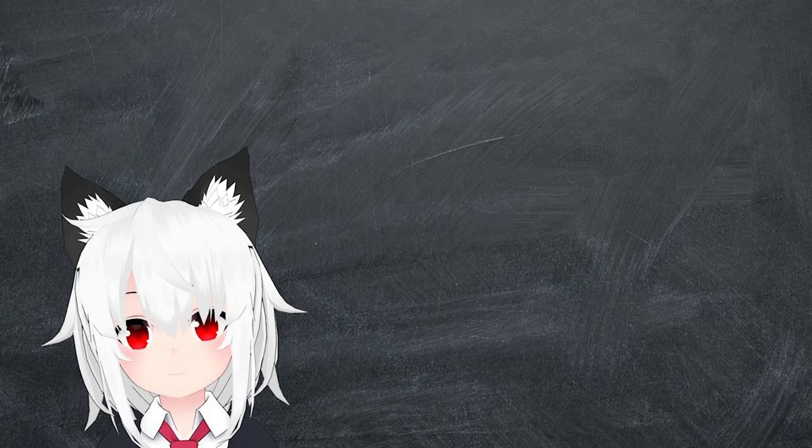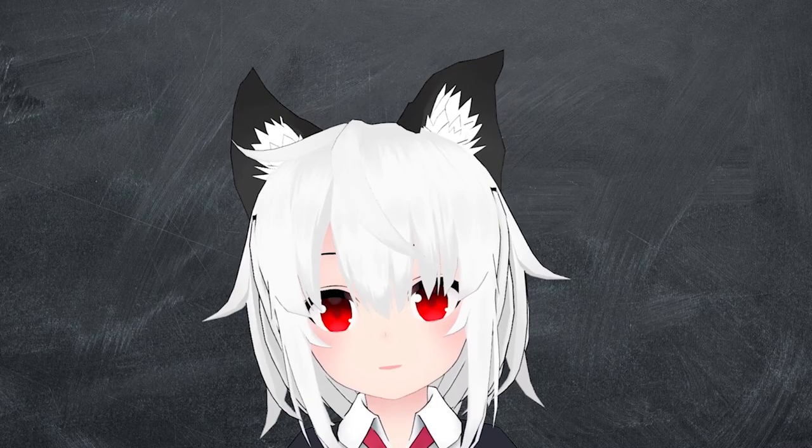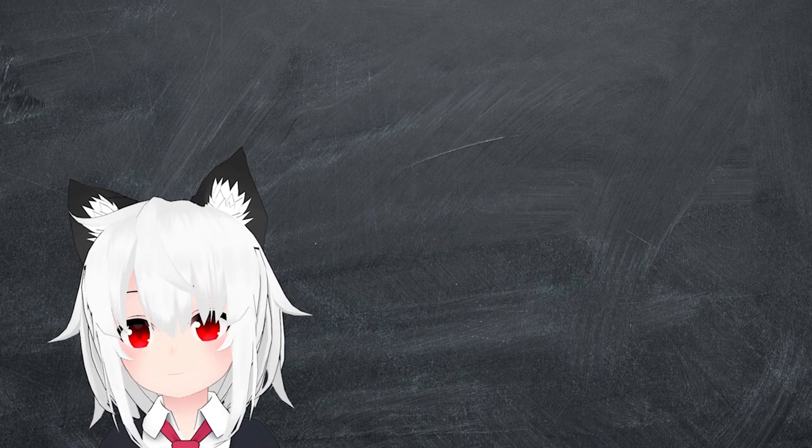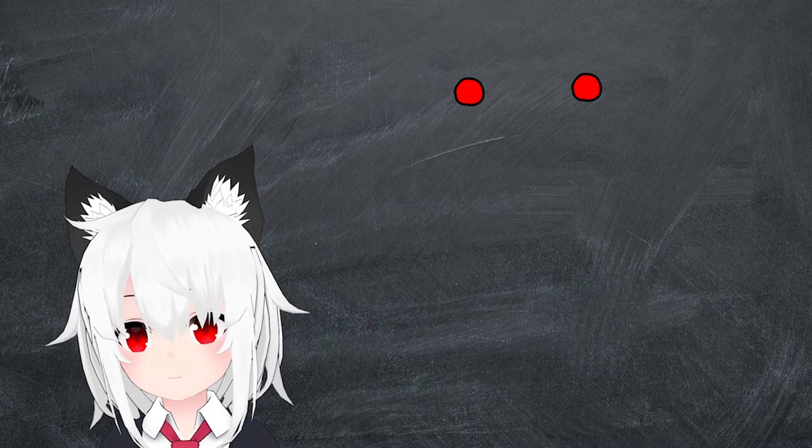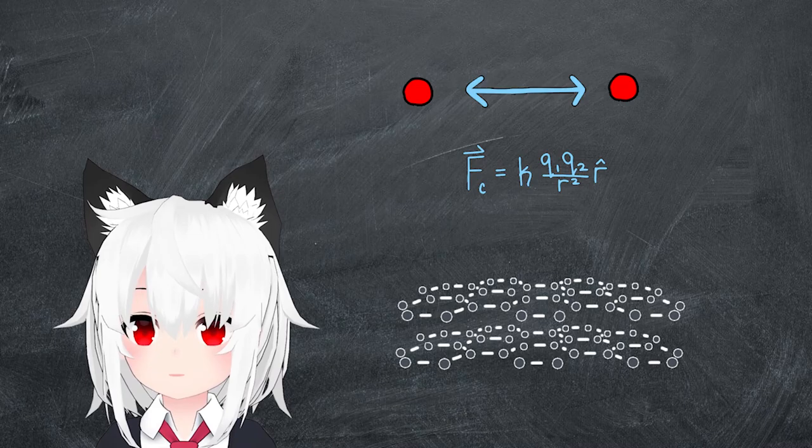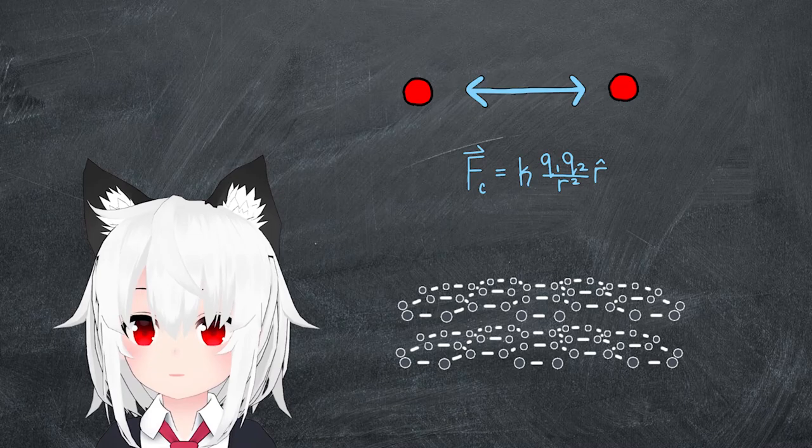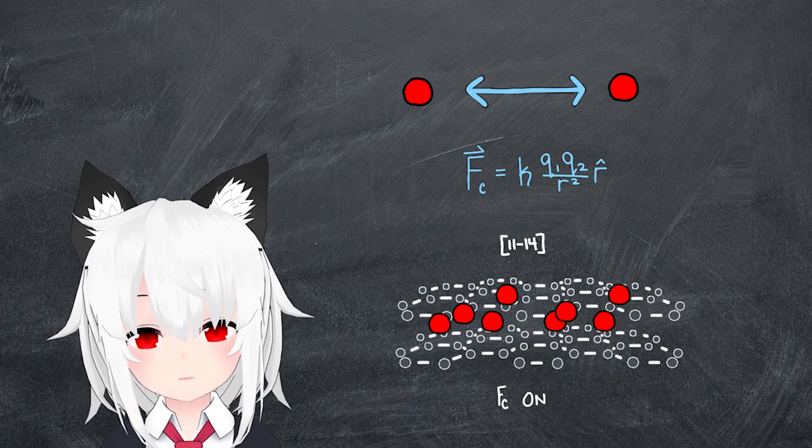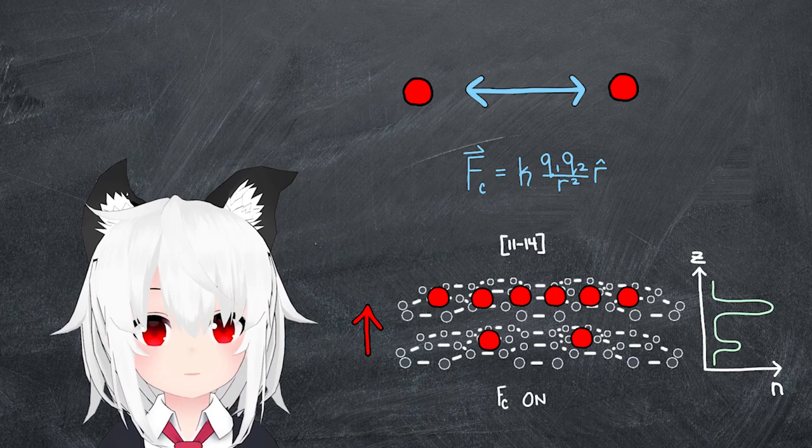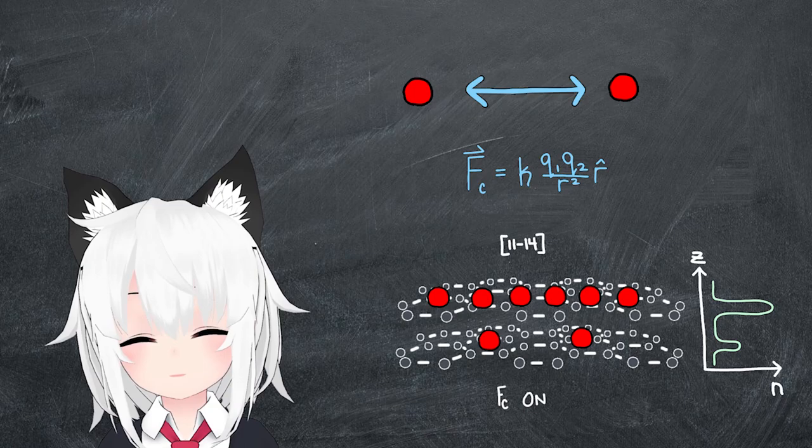But then, how do we explain the experiments? Well, if the experiments are true, then the only way around this would be to assume that there's some other physical mechanism, not captured by our simplified toy model, which ultimately ends up being responsible for the observed electrically insulating behavior. For us, since we're dealing with electrically charged particles like electrons, then this means that a good place to start might be with the familiar Coulomb force, acting as a sort of electrostatic force that repels particles of identical charge. In the particular case of few layer graphene, this force does end up being important, and can even be shown to modulate the equations of motion for the electrons in such a drastic way that they end up occupying some layers more densely than others. Ultimately, this gives rise to an electronic density modulation in the direction perpendicular to the layers, breaking inversion symmetry in this direction and modifying the material band structure accordingly.